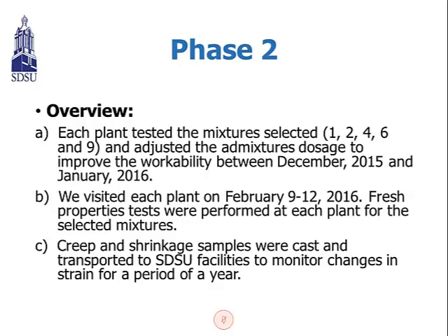So we tested the mixtures 1, 2, 4, 6, and 9, and adjusted the admixture dosages to improve the workability between December 2015 and January 2016. We visited each plant on February 9th and 12th, 2016, and fresh property tests were performed. And we also created the creep and shrinkage samples and transferred them to the SDSU facilities and monitored changes in strain over a period of 1 year.